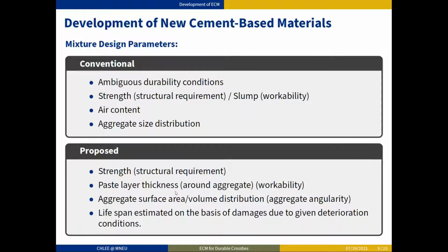So the idea is that, considering the aggregates in the mixture proportion, how thick do we have to coat those aggregates? As long as we can do it, we thought that controls the workability. And instead of simply aggregate size distribution, we thought about aggregate surface area and volume distribution. Then instead of the exposure condition, we thought about lifespan estimated on the basis of damages due to a particular given deterioration condition.